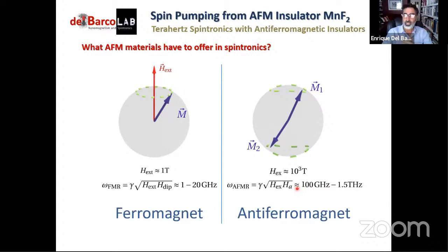And the way to think about this is, you think about an antiferromagnet in equilibrium, the two sublattices are aligned and anti-parallel to each other, and then we add the perturbation, we tilt the sublattice magnetizations slightly, we cant them into a given direction, and now they will feel a huge internal exchange field that will make them rotate very quickly.